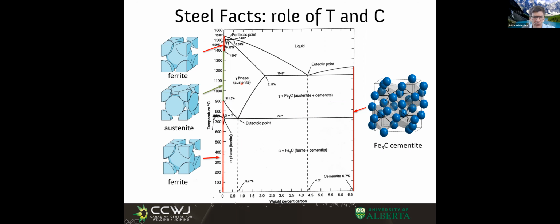So all austenite - that is iron with carbon in solution - has an FCC structure. Here, so thin that we cannot tell it from the red line, is ferrite - BCC iron with a little bit of carbon in solution, almost nothing. Carbon is pretty much insoluble in ferrite, very little. At this temperature, we can have it. This map also has some other interesting points.